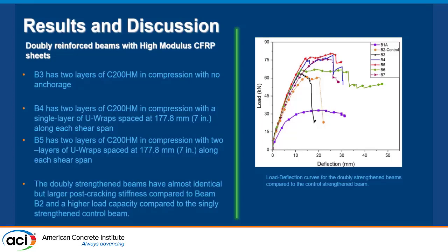So for the doubly reinforced concrete beams, we use beam 3 that has 2 layers of compression with no anchorage, and B4 that has 2 layers with a single layer of anchorage, and beam 5, just as a reminder, has 2 layers with 2 layers of anchorage. So we can see that the double strengthened beams have almost identical behavior, but larger post-cracking stiffness compared to beam B2, which was the control 1, and higher load capacity compared to the singly strengthened control beam. So they are also getting more load carrying capacity compared to the control 1, but have larger post-cracking stiffness compared to beam 2, which has no compression reinforcement.